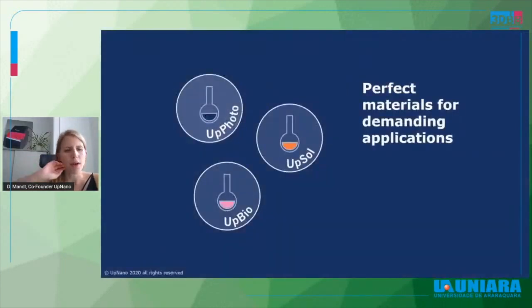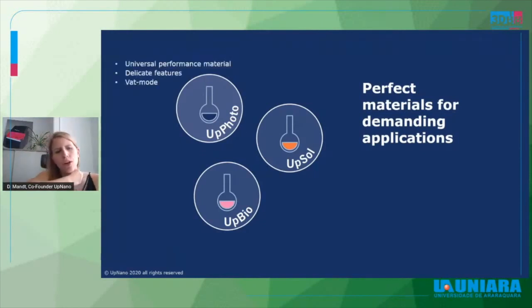The materials, I already mentioned shortly. We are offering at the moment 3 materials which are optimized especially for printing speed. We always tend to say the fast process also needs a fast chemistry, so the chemical reaction needs to be induced quite quickly, and also the hardening reaction has to be quick. With UpPhoto, we are offering a universal performance material. It can print very delicate features and is very suited for the vat mode.